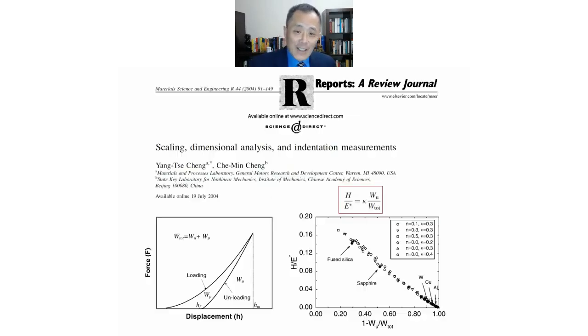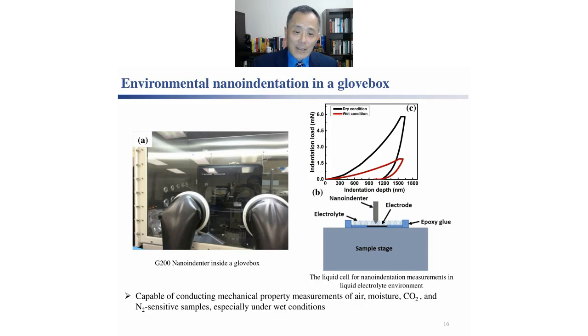And here we use nanoindentation, instrumented indentation, to measure the mechanical properties of the composite. Indentation is something that we worked on some years ago when I was active in the surface engineering community. And then here we use it for our battery research. We put a nanoindenter inside the glove box. Furthermore, we developed a sample holder that would allow nanoindentation of samples immersed in organic electrolyte.